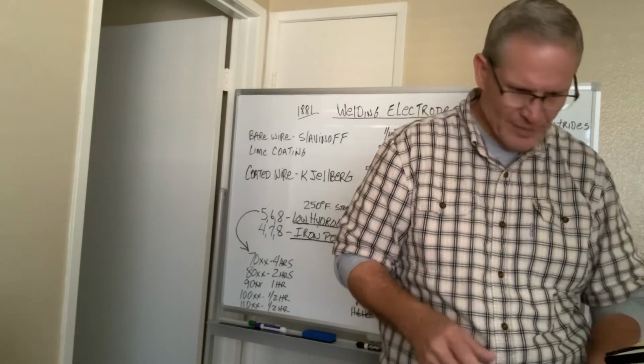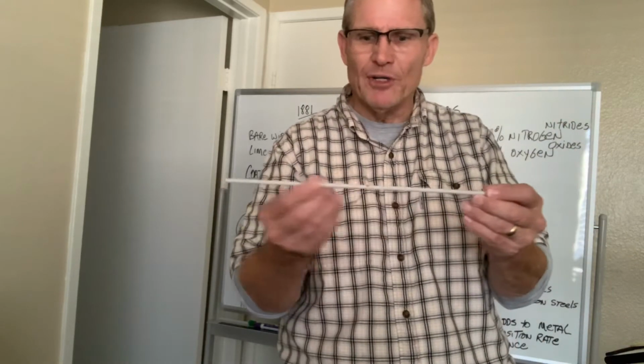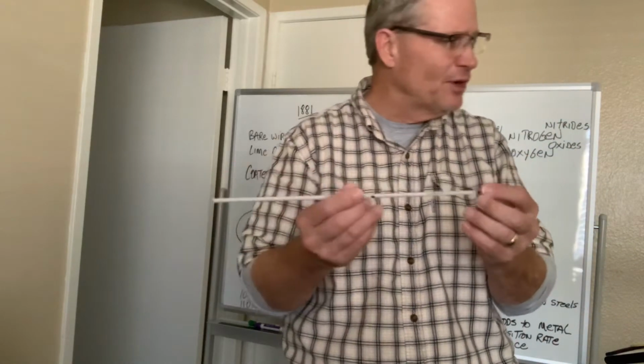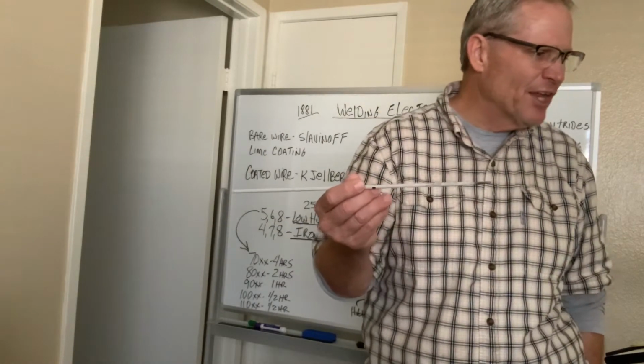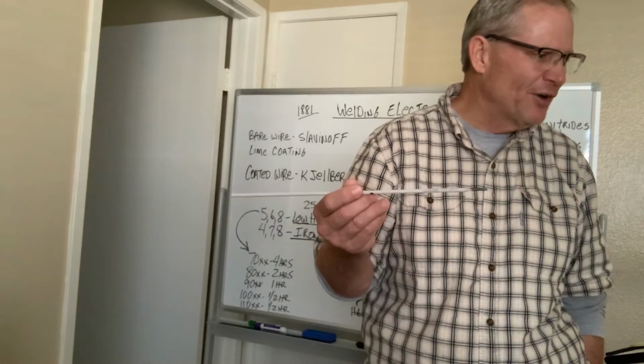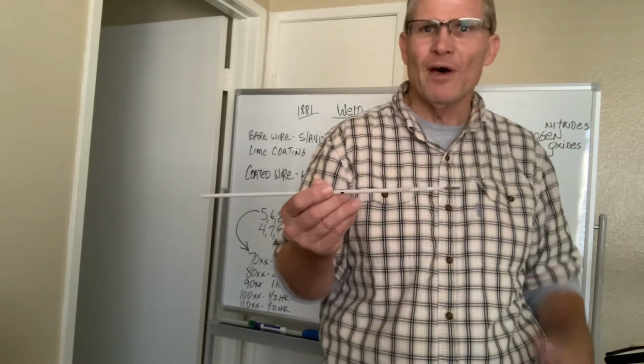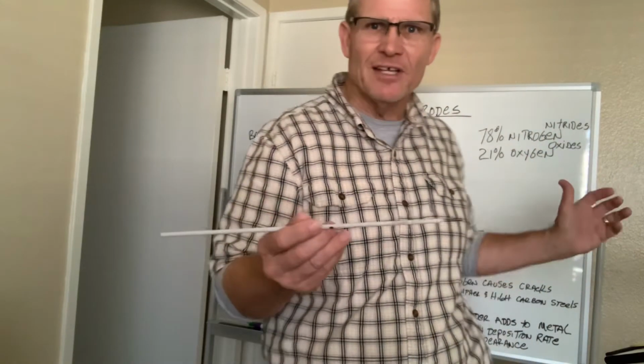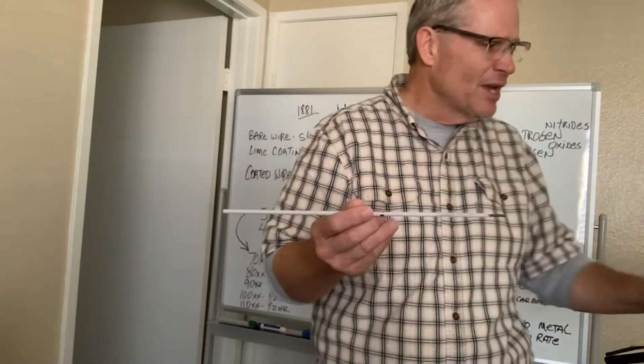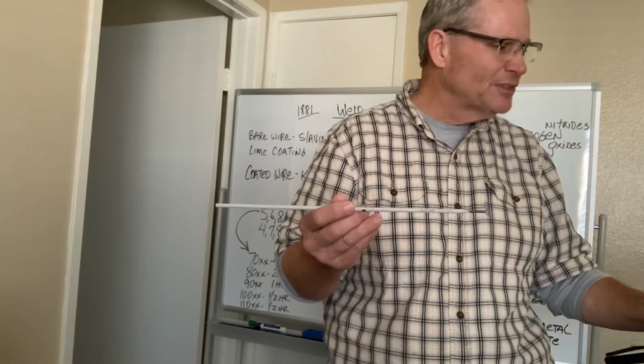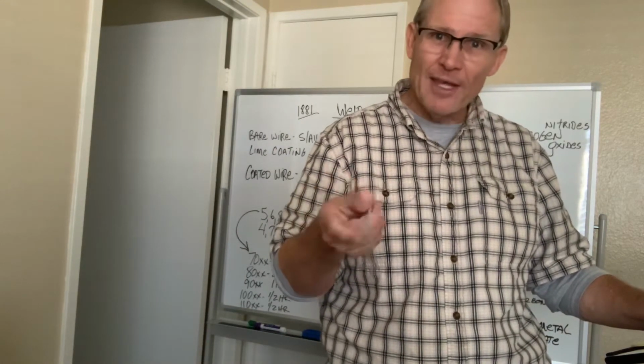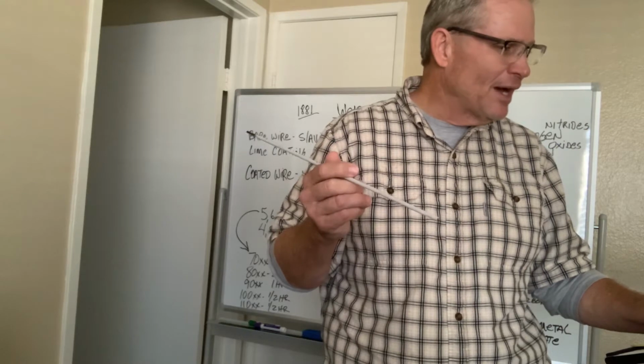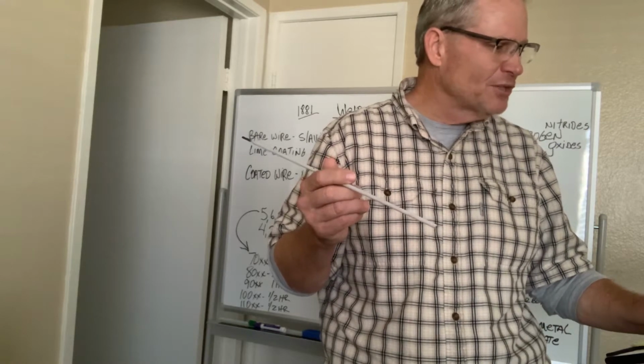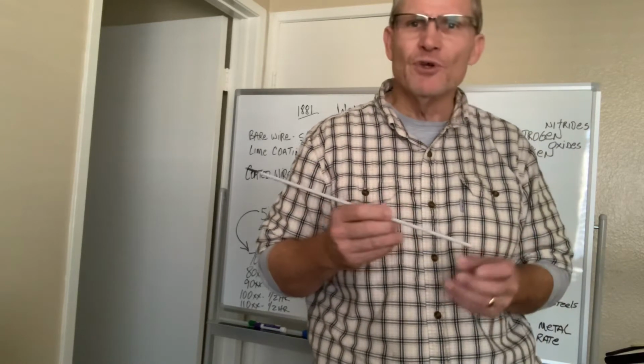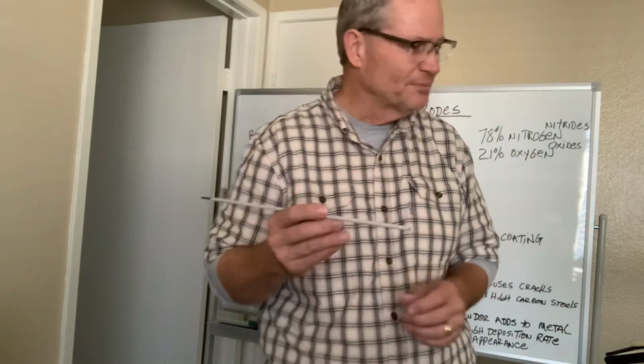Namely, as this coating burns on the outside of the bare electrode, it releases an inert gaseous atmosphere, and it protects the molten puddle from the nitrides and the oxides that I was talking about earlier. It also improves weld appearance. It's easier to strike the arc. You have a depth of penetration control, and you can produce X-ray quality welds.